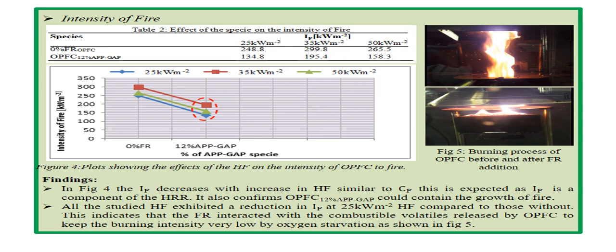The result obtained for intensity of fire. Figure 4 shows the effect of the heat flux on the intensity of the oil palm fiber composites to fire. The graph shows the intensity of fire decreases with increase in heat flux, similar to the contribution to sustain fire. This is expected as the intensity of fire is a component of the heat release rate. It also confirms the flame retardants could contain the growth of fire. All the studied heat flux exhibited a reduction in intensity of fire, with 25 kilowatts per meter squared heat flux showing the least value. This indicates that the flame retardant interacted with the combustible volatiles released by the oil palm fiber composite to keep the burning intensity very low by oxygen starvation, as shown.